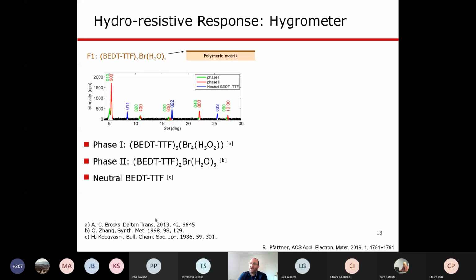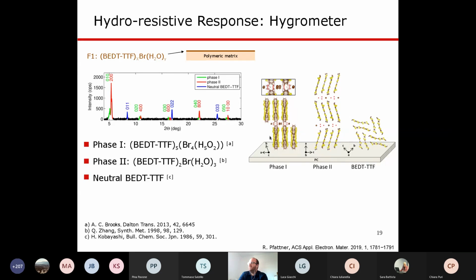And what we found is that there were much smarter people before us that actually did grow this type of materials individually and then analyzed them very carefully with XRD measurements, and they could measure the distances and how these molecules arrange. This schematic over here actually shows nicely how these calculations work. What they found out, they published in these papers, and then they submitted it to a database which we can now access. So we have a more clear picture of how the molecules actually orientate, and we can check that these same signatures can be found in our films. So now we know that we have two different phases, and our films are made up of these molecules. They arrange in this way, right? So there is the molecule, this is bromine, and there is some water in between.